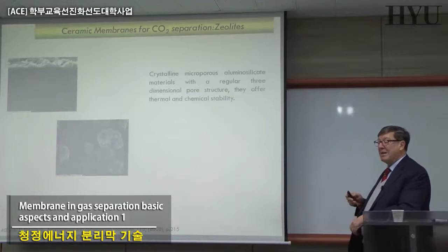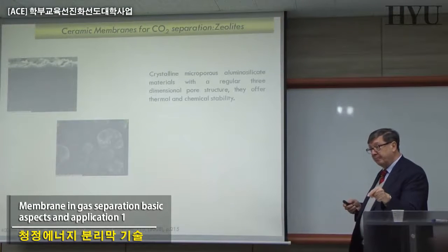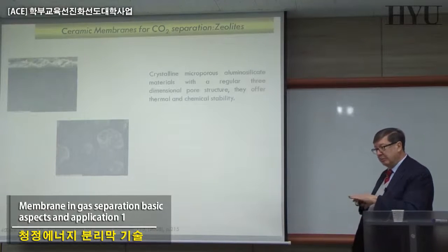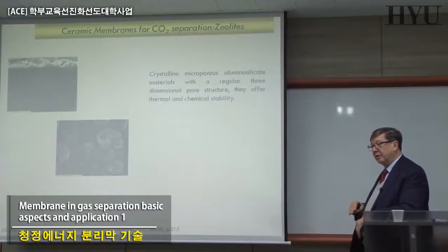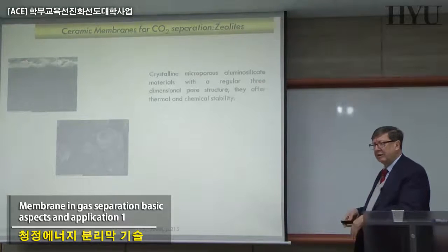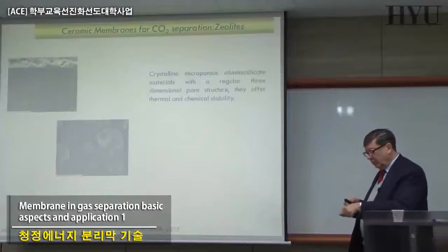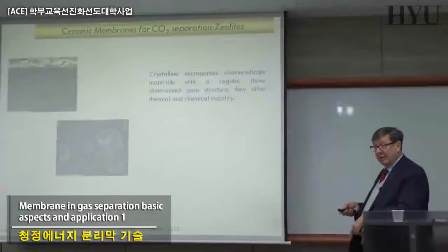So the wettability of the zeolites in a polymer matrix is one of the problems under investigation. Today, more and more, however, researchers are able to grow this layer of crystals of zeolites on some support in a relatively very regular structure with no defects and no holes, and so the zeolites can operate.